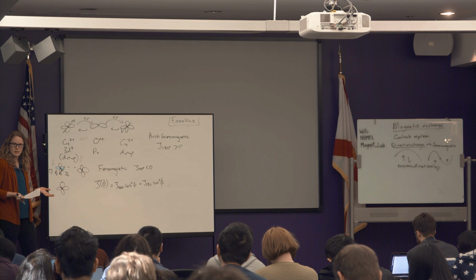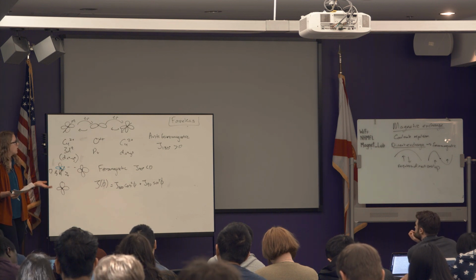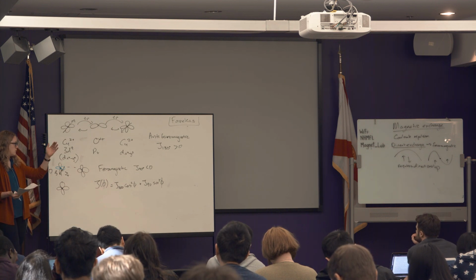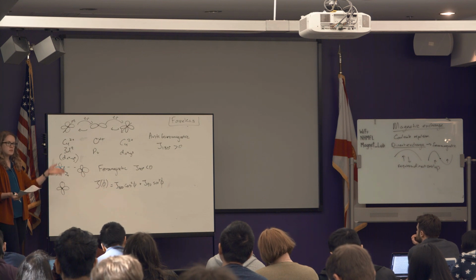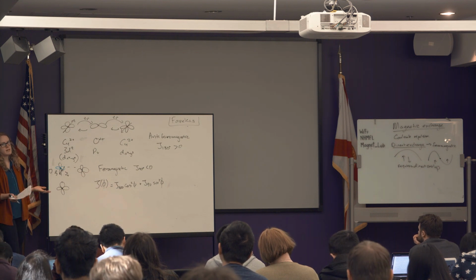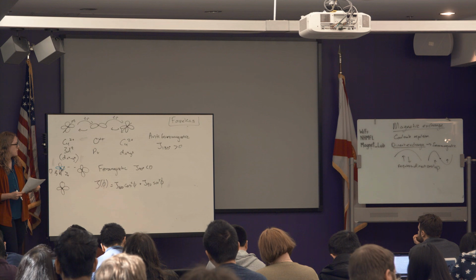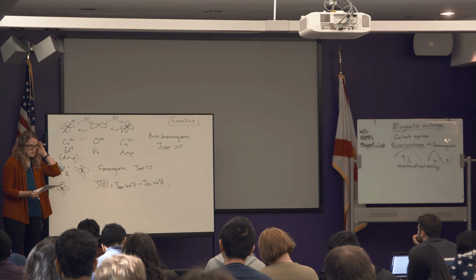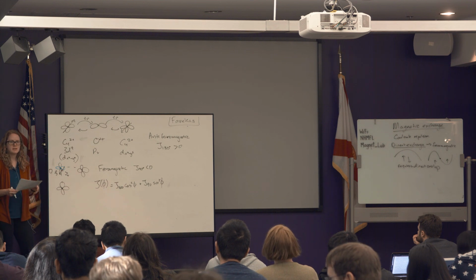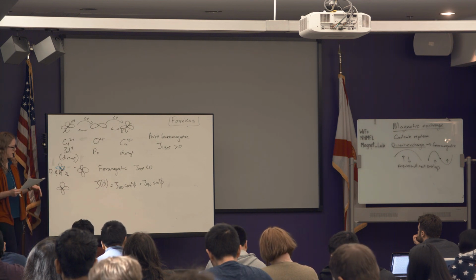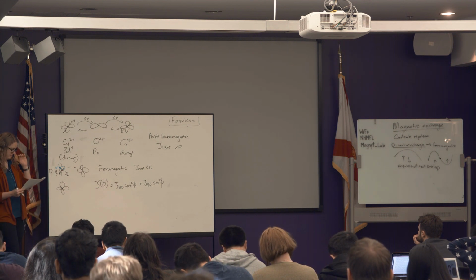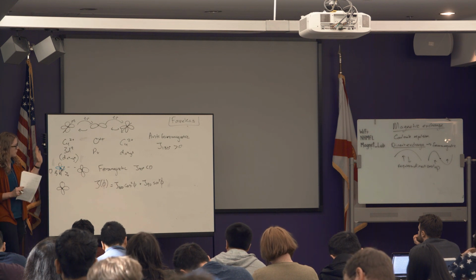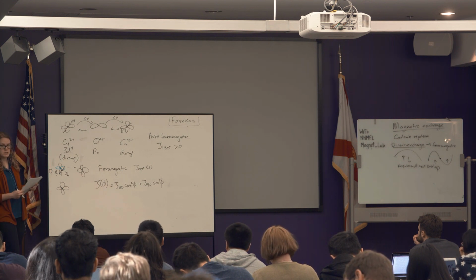So if you're looking at any given crystal structure, you can see where your transition metal ions are, you can see where your oxygens are, and so you can look at the different superexchange paths and you can estimate what J's you think are present and roughly what orders of magnitude they are and what signs they are. So this is a useful tool for getting a rough sense of what kind of model you might get. And all of these so far, however, are giving you Heisenberg exchange.